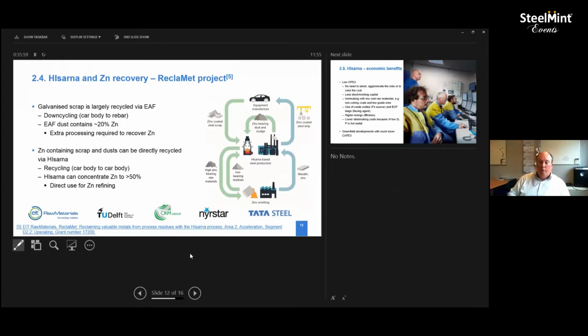And on the zinc recovery, this is also part of a European project under the EIT raw materials banner, and together with Nyrstar, who is one of the suppliers of zinc to the steel industry. And what we do is, in integrated steelmaking, we try to avoid the use of zinc-coated scrap, because the zinc is released as dust and vapor in the steelmaking process, and most plants recycle that dust via the blast furnace, and zinc in the blast furnace can be a real problem. So for that reason, they tend to avoid the zinc-coated material, or put it through a de-zinking stage first.